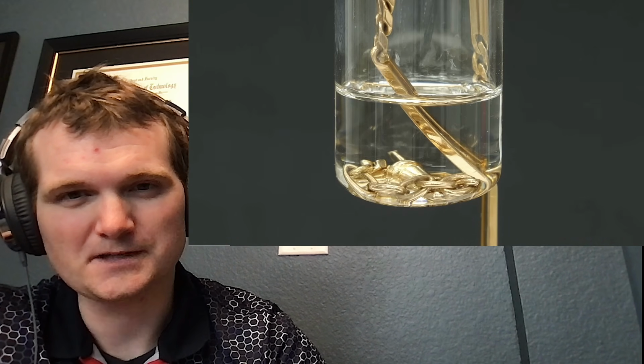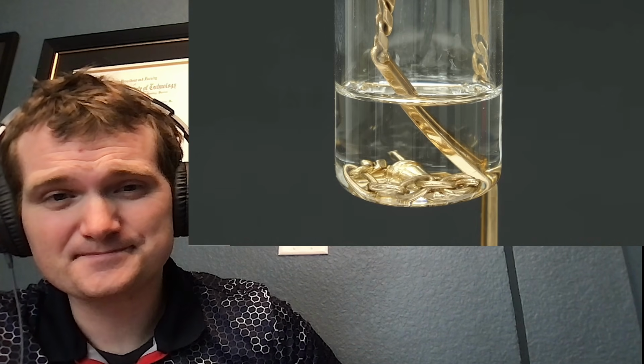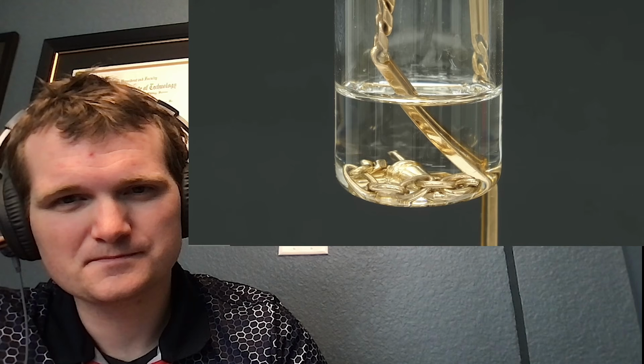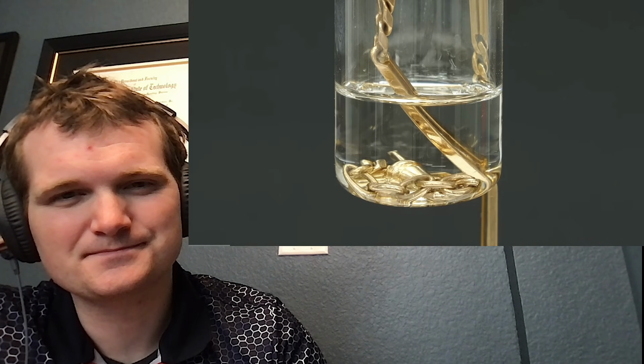Nitric acid is able to react with very malleable metals and dissolve them, but some metals like gold are really resistant. At lower karats, below around 8 or 10, the acid can eat around the gold atoms and dissolve the other metals. However, when we start getting up to 12 or 14 karat, the gold is able to block the acid. This is why, even after sitting here for a few minutes, pretty much nothing happened. A deep scratch also didn't do anything either, so together, this told me that not only was it not plated, it was probably at least around 14 karat.